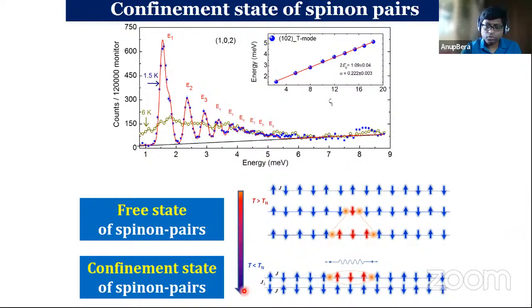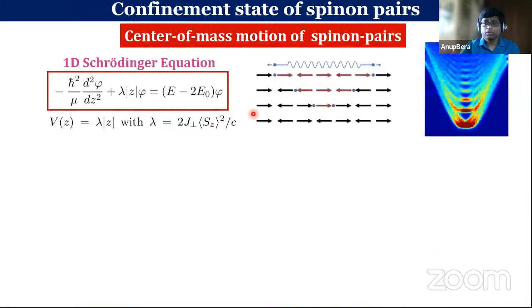But as soon as we go below the ordering temperature, the chains are not free now. They are coupled to the nearer chain, so there is an interchain coupling. Now, if I want to move the spinons apart, then we have to break the exchange interaction between the chains, which provides the potential for the confinement of the quasi-particles. So this interchain coupling effectively provides the potential for confinement. And as soon as we break these bonds, 1, 2, 3, we get these energy states. So this is the confinement of spinons.